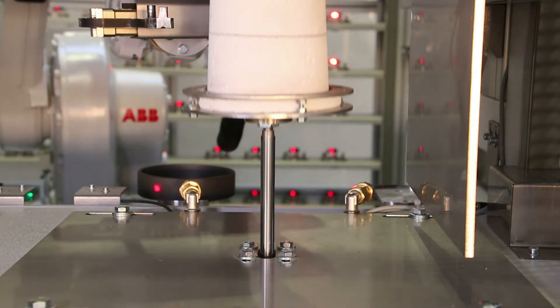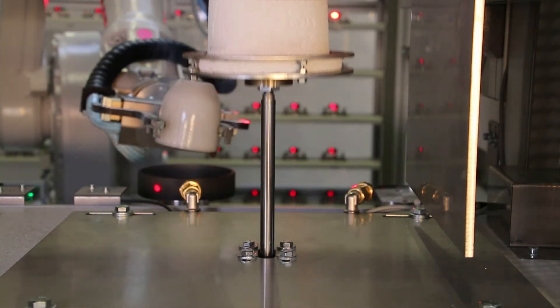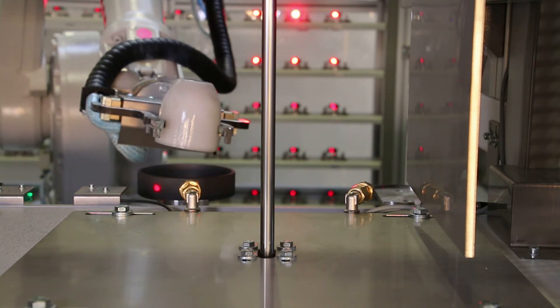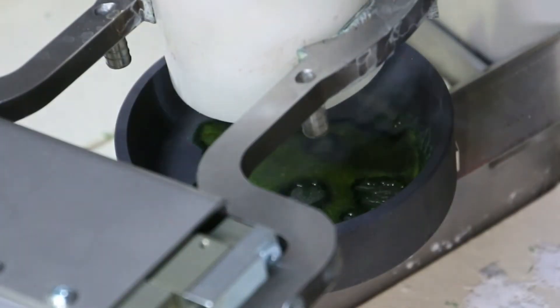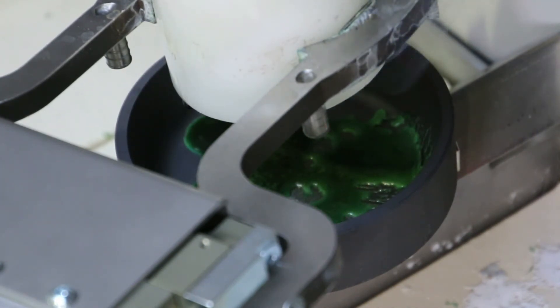After the fusion is completed, the robot pours the melt into a special dish for cooling. All processes are optimized and timed to ensure complete discharge of the crucible and to minimize the sample residue. The casting dishes are constructed in such a way that the melt cools down quickly and prevents the sample material from sticking to the wall.